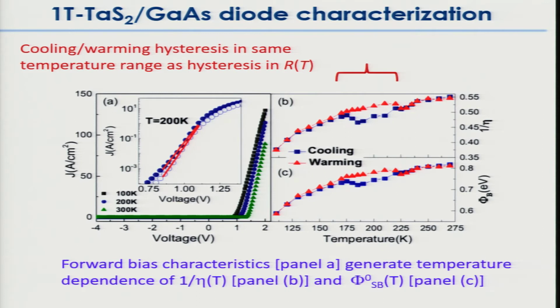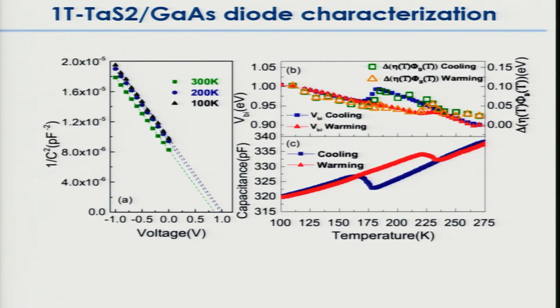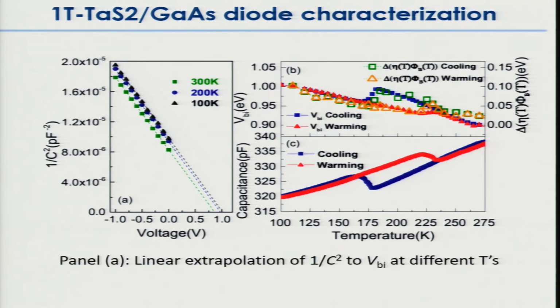Okay, and we're doing it from the forward bias characteristics. We can also do the same thing from the capacitance characteristics. This is going to the reverse bias and measuring it directly. And you see here, let me bring down first panel A here on the left. It's showing you the linearity and the nice extrapolations to VBI. 1 over C squared to VBI at different temperatures. So we do this at different temperatures, and you could do it as a function of temperature. And we plotted the VBIs as blue squares and red triangles on this plot. And this is where the CDW is forming.